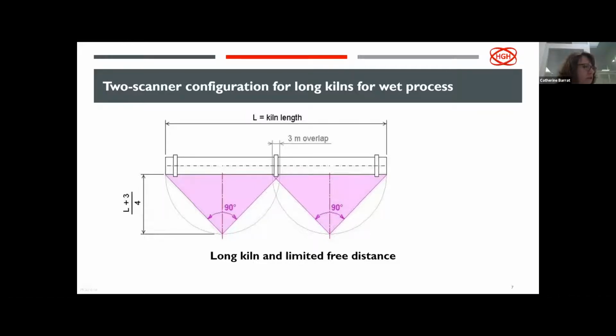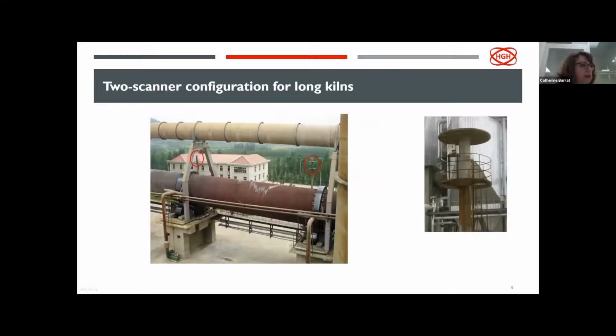In that case, the kiln scanners are located approximately at a distance of the length of the kiln divided by 4. And this is, for instance, a typical configuration with two 90-degree field of view line scanners. There is a picture of such an application here in this plant. The two scanners are located at the top of a mast and they aim at two distinct portions of the kiln shell, and the two images from the kiln shell are combined to create the complete kiln shell temperature monitoring.